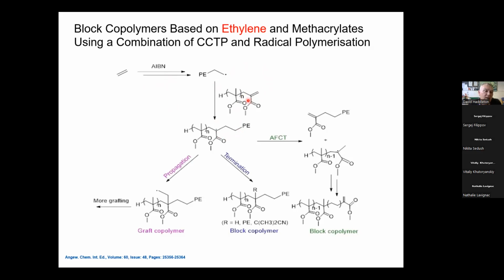Now, if that was another methacrylate, I'd end up with fragmentation, a RAFT process. I end up with a living polymerization. Well, anyway, this could do a few things. We can either just carry on propagating, so we end up with polyethylene, like a three-arm star with one arm methacrylate, two arms polyethylene, or it can just terminate by abstracting a hydrogen atom, which would be ideal, because then that's got an AB block copolymer where the polyethylene block is however long that was, and we control that by the ratio of initiator to monomer, or the pressure of the monomer actually, and we control the length of the other block by whatever we decided to make.